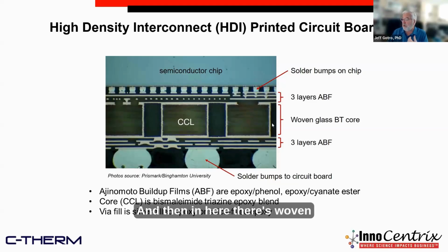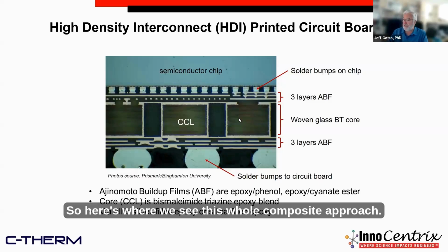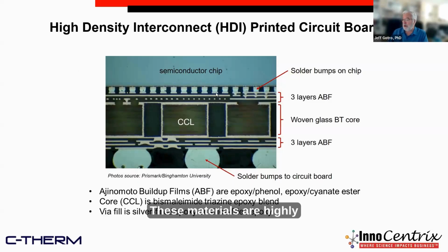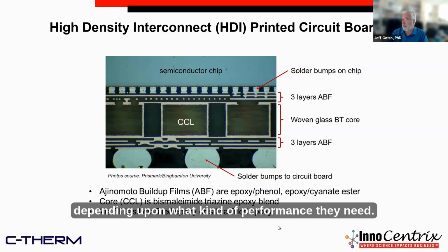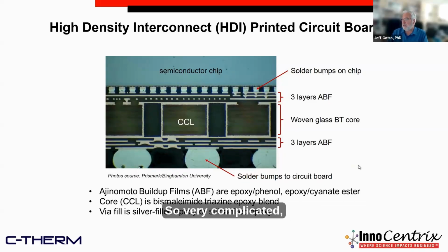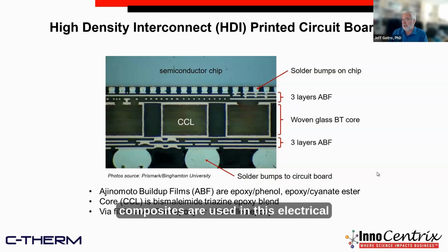And then in here, there's woven glass. So here's where we see this whole composite approach. These materials are highly filled. These have woven fabric in them, and then more layers of this buildup film on the bottom. And so there's a number of different technologies involved: bismaleimide triazine epoxy resins, epoxy phenolics, epoxy cyanate esters, and then these vias can be filled with silver-filled epoxy or silica-filled epoxy, depending upon what kind of performance they need. So very complicated, but highly engineered composites are used in this electrical interconnect world.